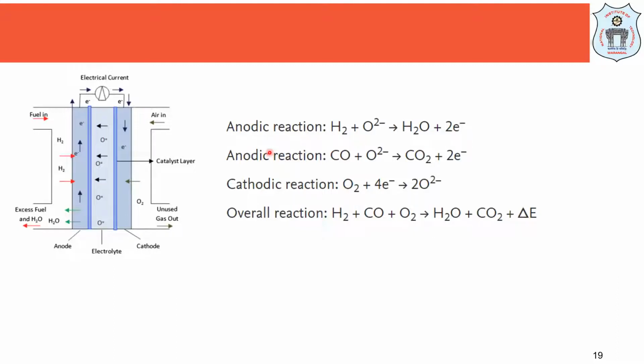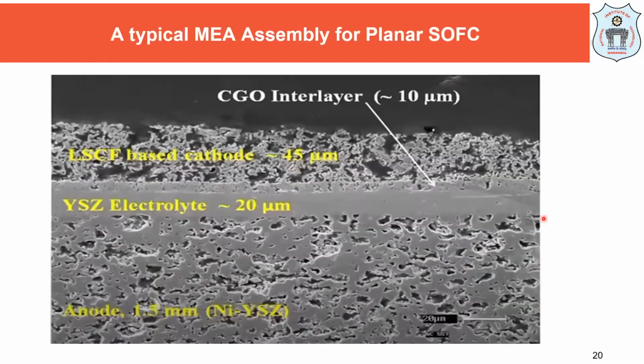So what are the reactions taking place if you are sending a combination of hydrogen and carbon monoxide? Then you will have hydrogen forming water and electrons, and if carbon monoxide is there, that is also consumed in this reaction at the anode side. So carbon monoxide and the oxygen anions will combine to form carbon dioxide and release electrons. And in the cathodic reaction, as we have already seen, oxygen will react with the electrons that are reaching it to form oxygen ions. And the overall reaction, when we use a hydrogen and carbon monoxide mixture as the reactant entering the anode side, is H2 plus CO plus O2 giving H2O plus CO2 with release of energy, heat also. So we know that the reactions are exothermic. That heat has to be utilized well. So that is the objective.